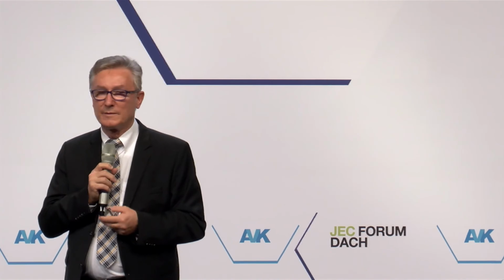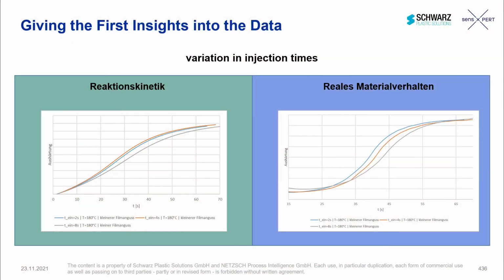And finally, we did the same material, but we took different bags, because out of experience, we know that even one bag to a second bag might have a big influence in the processability. And that is what we want to show you now with the next 4 slides, with the deviations we've performed to see the difference between pure reaction kinetics on the left side and the real material behavior we've measured within the mold.